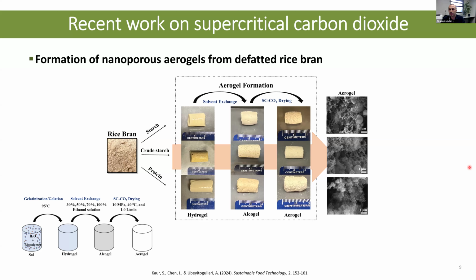So, another application we did with CO2 is to create aerogels, and I have been doing this for a while now. So here we looked into defatted rice bran. So what happens in the rice processing industry? They remove the bran, and then you generally do an extraction to remove the rice bran oil, and then you end up with this defatted rice bran, which is really underutilized. And we looked into how we can upcycle it and create high value materials. And in this case, we created aerogels with a really high surface area and porosity that can be used for delivery of micronutrients.